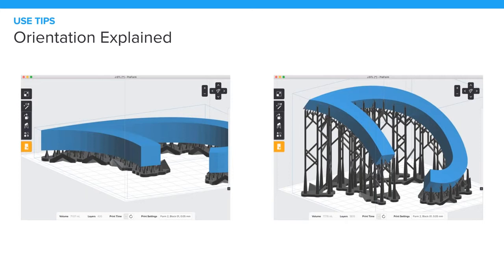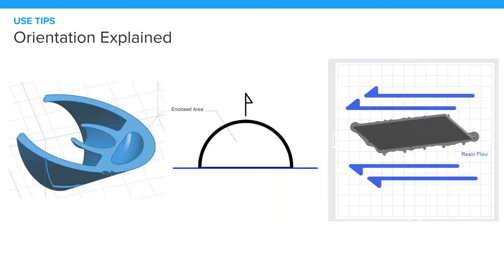So in cases like these, with a long flat component, and in general, you should tilt your part up like in the second image. That's reducing the peel forces, reduces the amount of supports you need, and the general rule of thumb here for orientation is that you try and have as much of your part build off itself as possible and minimize each layer's surface area that makes contact with the bottom of the resin tank, thus reducing those peel forces. So let's get through the images on this page, and then we'll jump into the practical demonstration.